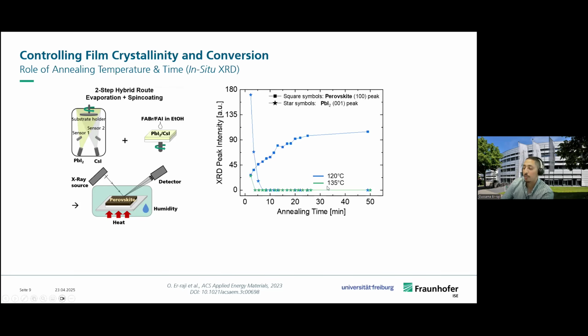And then what happens when we increase the annealing temperature is that the amount of lead iodide that we detect at the beginning is much less compared to that at 120 degrees. So this shows us that we already have a speed-up taking place. The crystallization becomes a bit faster, and the full conversion happens in less than 5 minutes compared to 7 minutes or a bit higher at 120 degrees. And secondly, we see again that with the annealing time, the perovskite peak increases until stabilization.